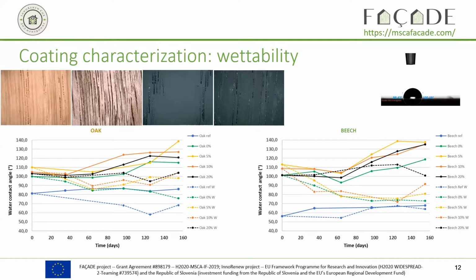Here you can see some pictures of oak that is not coated initially, at the very left. So you can see that the surface is quite porous already at the beginning. And the second picture, it's after 5 months of weathering when it's unprotected. So we can clearly see the erosion of the surface, and that the porosity is increased a lot.